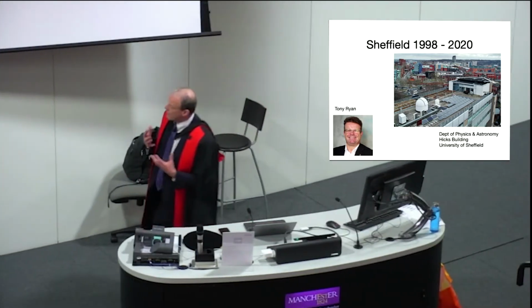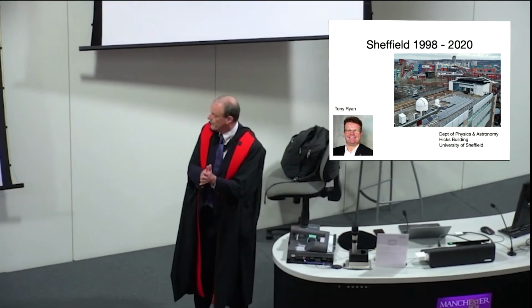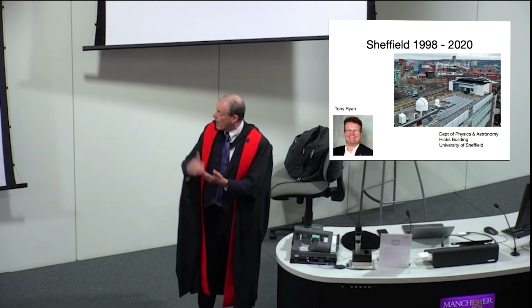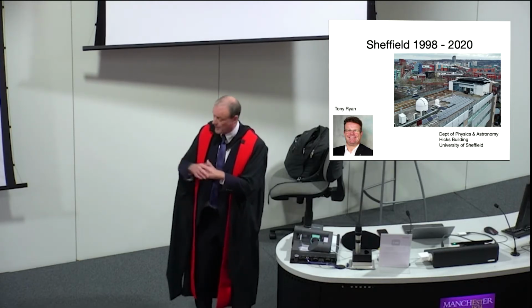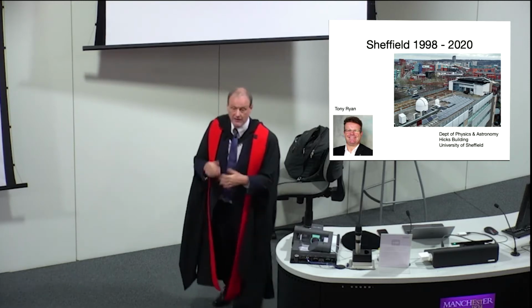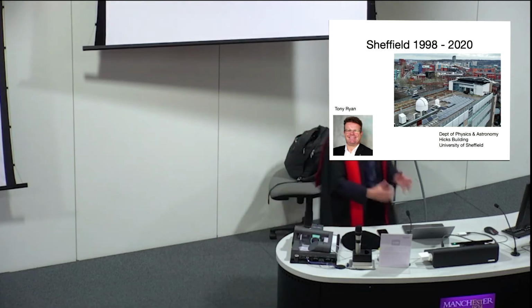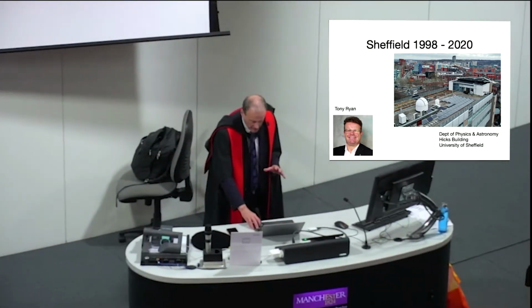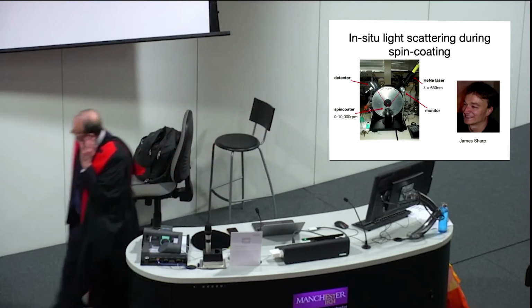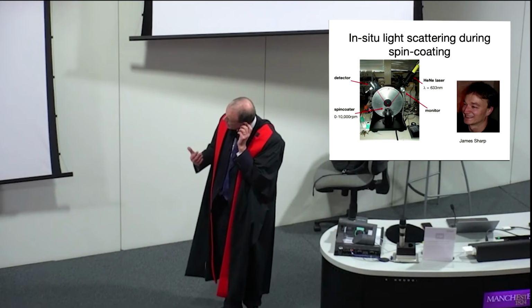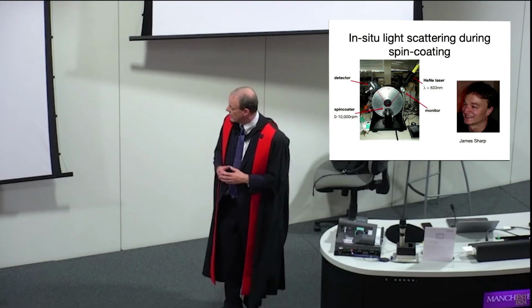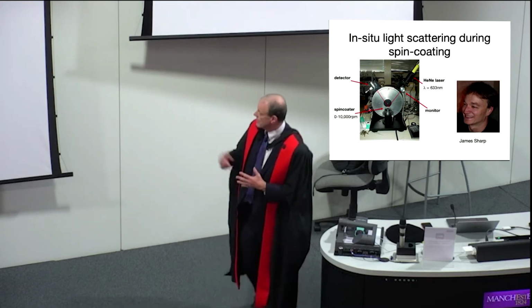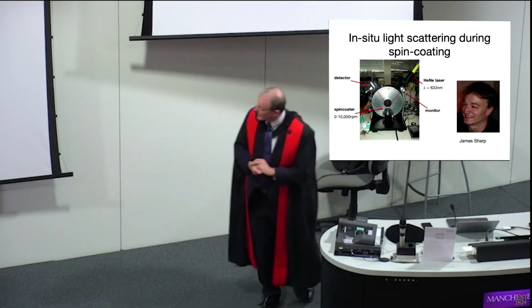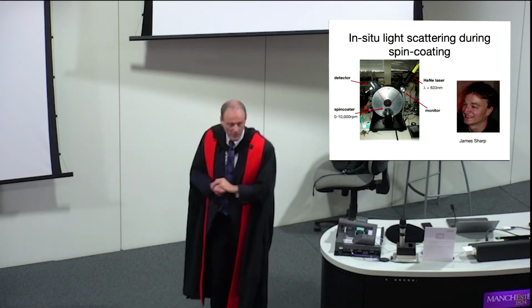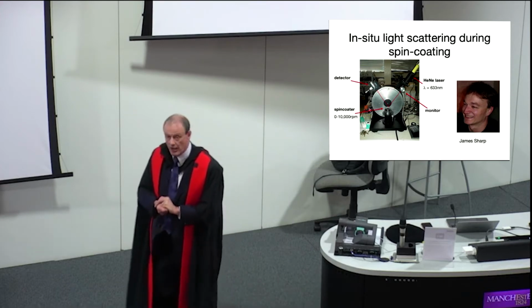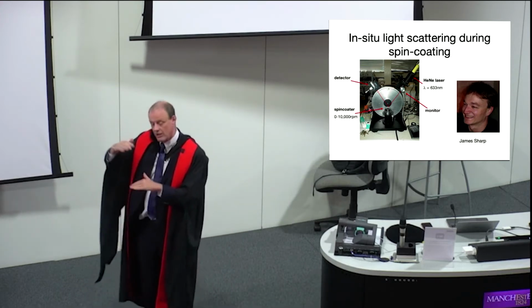So I went there with this idea: we know you can get interesting and useful effects by having thin films that phase separate, where the phase separation is modified by the surface or the interface. But what we need to know is what's actually happening in the process. So we built a device that allowed us to study what was happening during spin coating. James Sharp, a student and then a postdoc, now a lecturer in Nottingham, did a great job of making what we lovingly called the optospinometer, basically an instrumented spin coater that allows you to look at light scattering in situ as you make the film.